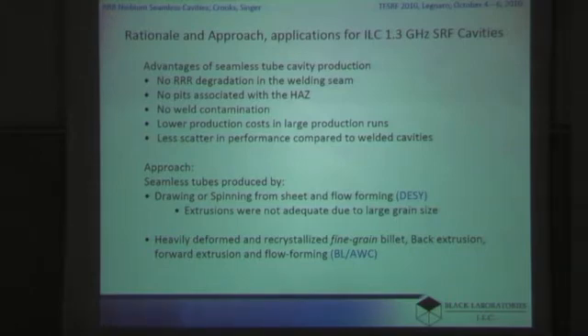I don't know the specific percentages, but of the ILC cavities that have been manufactured with a target accelerating gradient of 30 to 35 megavolts per meter, quite a large number have failed in the 12 to 15 megavolts per meter region due to thermal quenching associated with pits. And this might have to do with contamination. It might have to do with other problems associated with recrystallization near the weld. The weld itself is a problem in that it's not smooth and might contribute to magnetic field enhancement at the equator. The approach here, we've used really two approaches.